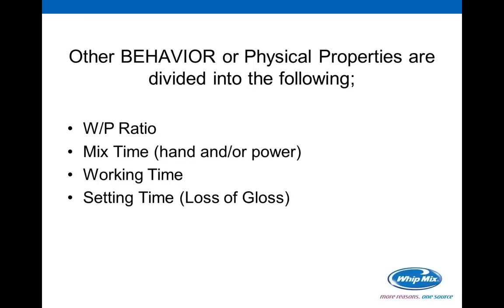Set time is purely when we have what is called loss of gloss. You've all experienced that. Once you mix a stone product up and pour it, it'll still be wet and shiny on the top. At some point, that shininess goes away. That's your loss of gloss. That's the set time. However, it is not the time that you can remove it from your impression. Most stones, and that includes die stones and dental plasters, should be removed somewhere at a half an hour and then past that point in time. But generally, it should be a half an hour minimum, unless it is a stone which has been designed specifically to set at a faster rate of time.